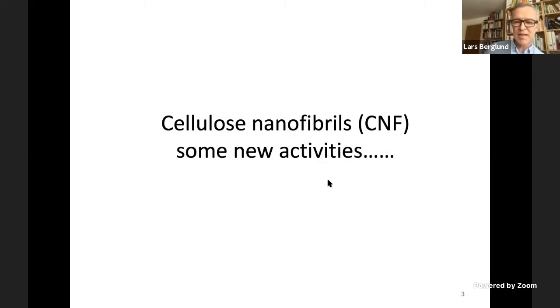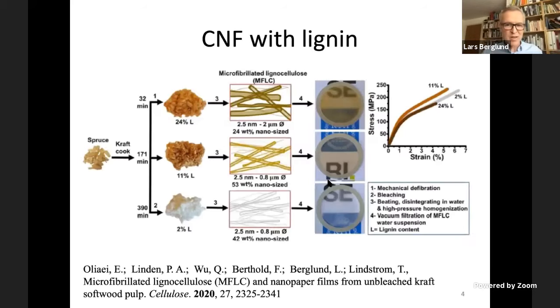So I wanted to start then with cellulose nanofibril activities in our group. This is obviously still very interesting because we are basically creating small building blocks that can be used to shape completely new material structures. One of the interesting new things is to try to make fibrils which still contain lignin. So this is work in collaboration with RISE, Fredrik Berthold, Tom Lindström, and Erfan Oliaei is the student working on this. So as you can see, he starts with unbleached kraft. And the hypothesis was that it would be possible to find an optimum in lignin content and in charge, so that it would still be possible to mechanically disintegrate fibrils, although there is lignin in the fibers where we start.